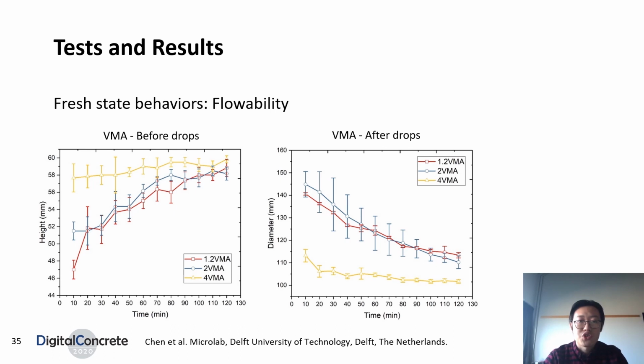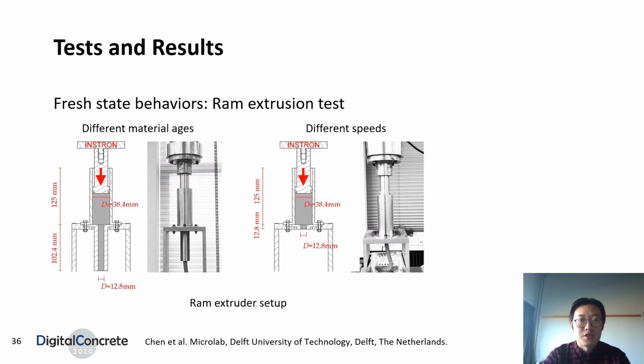For the mixtures containing VMA, the workability loss with time is also evident. Increasing VMA dosage could enhance the shape stability and the retention of the demolded sample. The next test is based on a RAM extruder setup. 2 specific tests were performed to study how the extrusion pressure changes with time and how it changes with different RAM speeds.